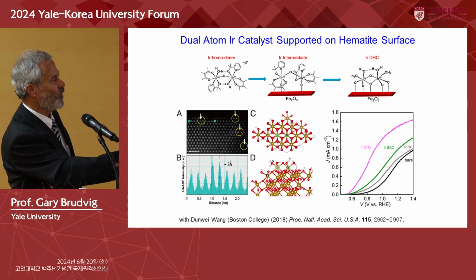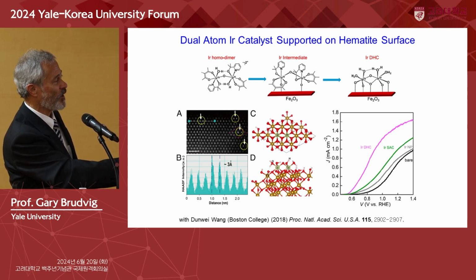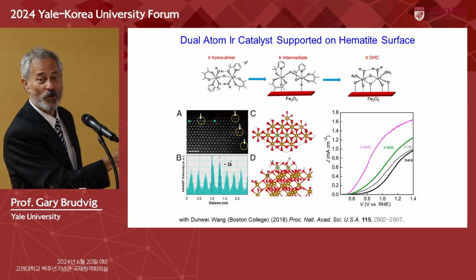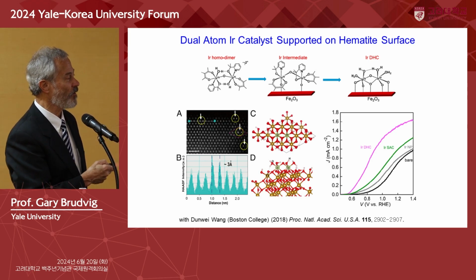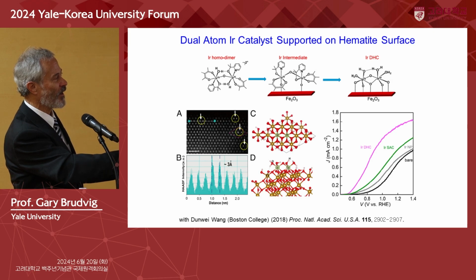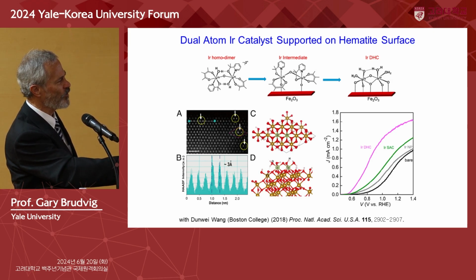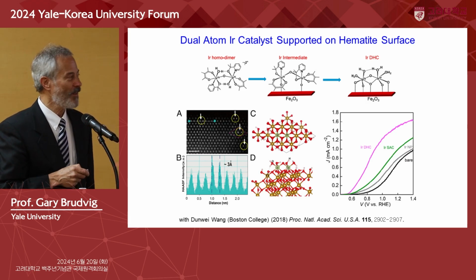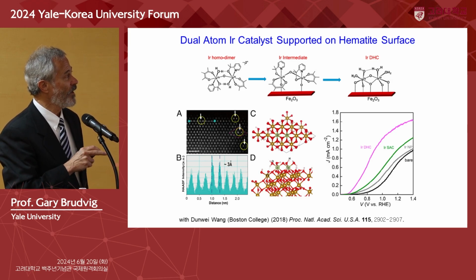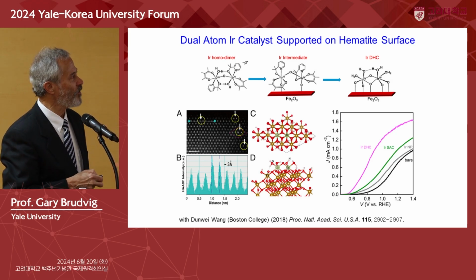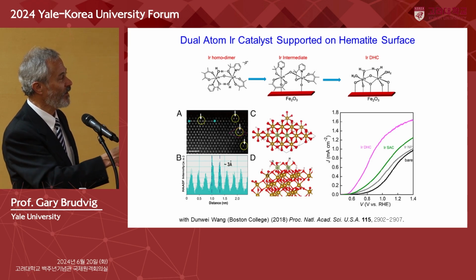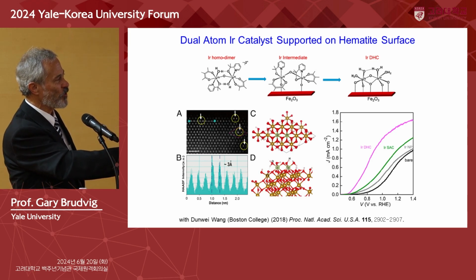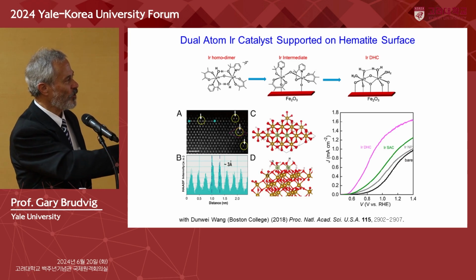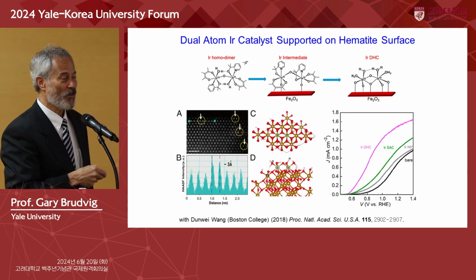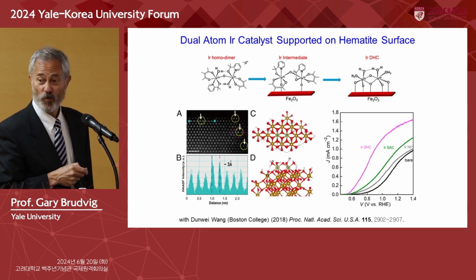And this just shows some photocurrents where we take the hematite by itself. We can put nanoparticles. As I mentioned, iridium oxide nanoparticles is the best heterogeneous catalyst based on oxide nanoparticles, and it slightly improves. We can put a single atom catalyst, and it slightly improves better, but the dimer is much better. And I think there's two reasons for this. One is this is a 4-electron reaction, and two metals can help facilitate that. I'll show in a minute the difference between single atom catalysts and this DHC, or dual heterogenized catalyst, is stability as well. And the dual atom catalyst is much more stable.